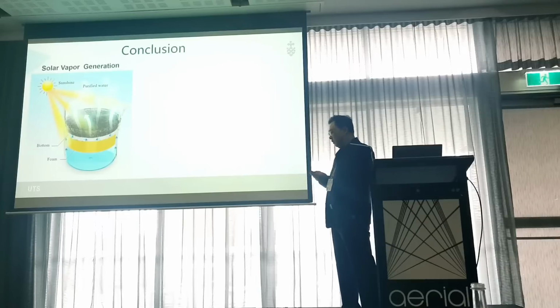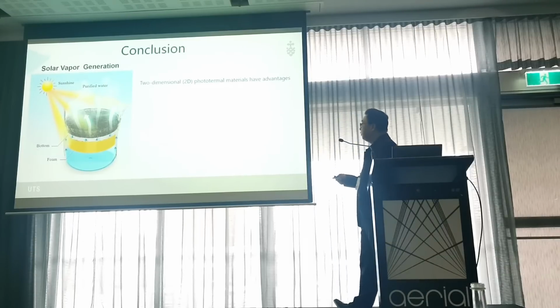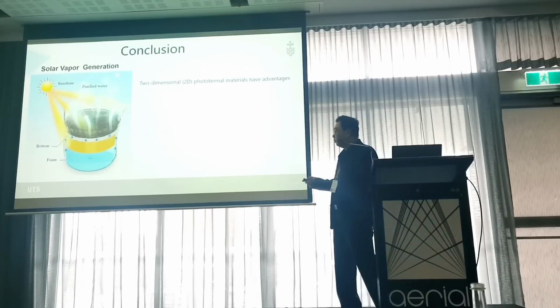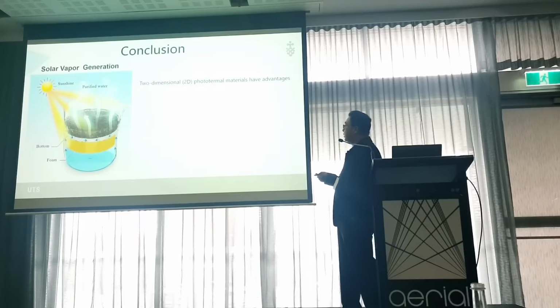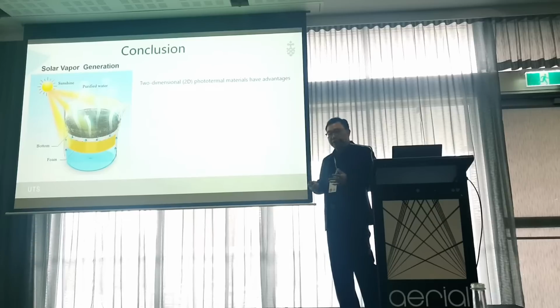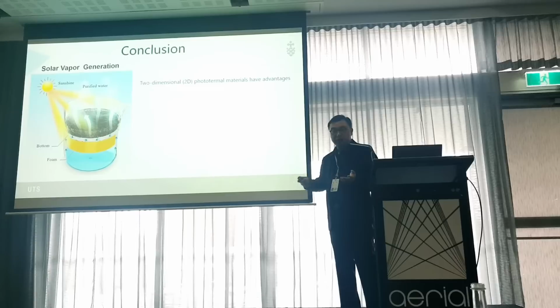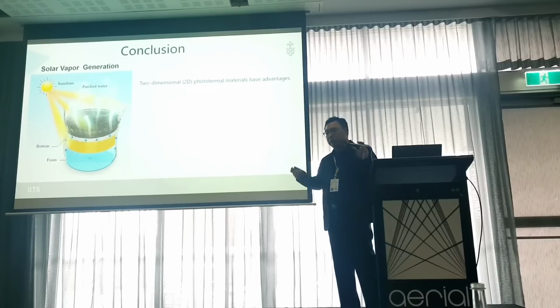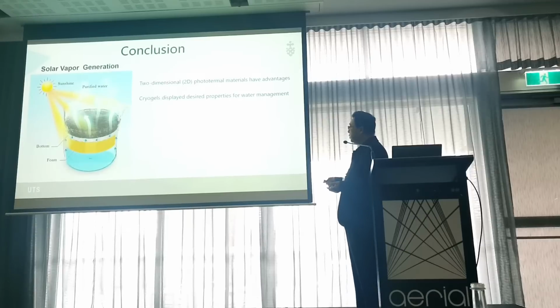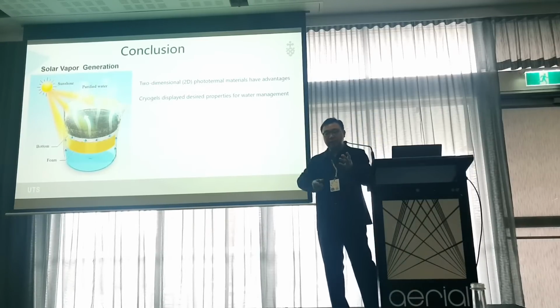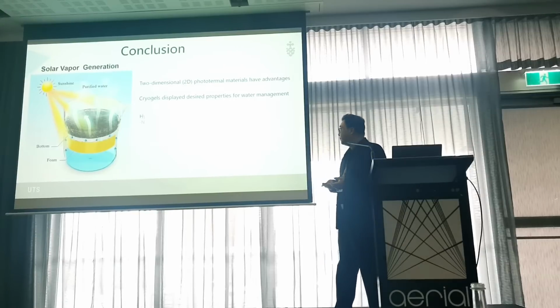So finally, to give a conclusion. Firstly, through our study, we found that 2D materials have a high aspect ratio. Therefore, they have some advantages compared to 1D and 3D photothermal materials, because we only need 1/10 of the weight, which saves some money. And secondly, the cryogels also display the desired properties, like large pore size and interconnected pores.